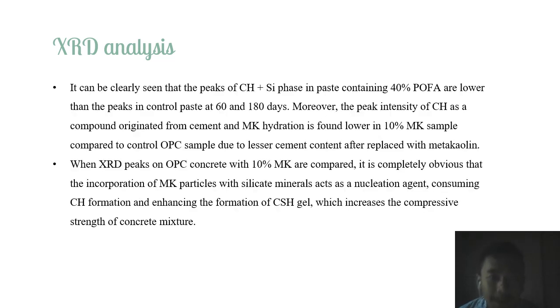It can be clearly seen that the peak of the CH plus Si phase in the mix containing 40% POFA is lower than the peak in the control at 60 days and 180 days. When XRD peaks on OPC concrete with 10% of metakaolin are compared, it is completely obvious that the incorporation of metakaolin particles with silicate minerals acts as a nucleation agent, consuming CH and enhancing the formation of CSH gel, thus increasing the compressive strength of the concrete mixture.